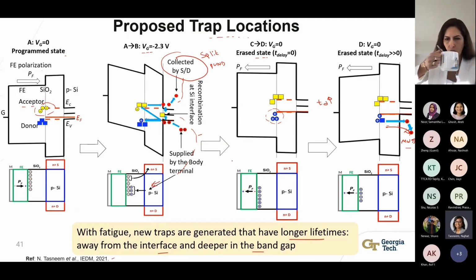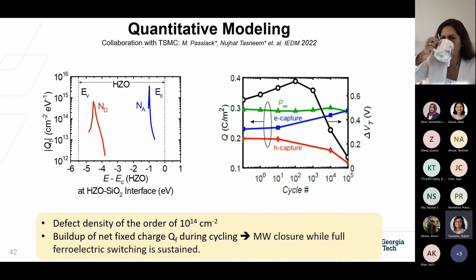I want to briefly show you here our work in collaboration with TSMC, where we used the results from our split pulse technique and tried to propose a quantitative model for FeFETs that reflects the trap dynamics and their role in the device operation. So using this model, we were able to quantitatively extract defect densities, which are essentially discrete and in the order of 10 to the power 14 per centimeter square, which is pretty large. Also, they are in the vicinity of the silicon oxide interface.